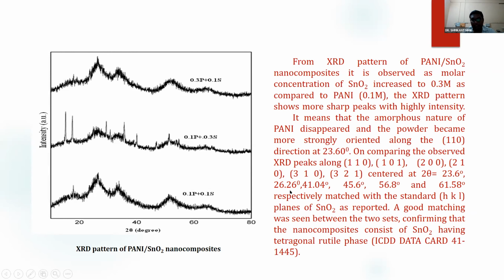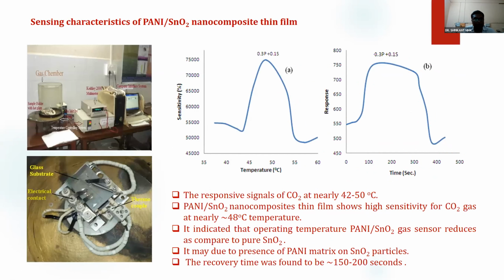And I compare this data with the JCPDS card number 41, which confirms the reported SnO2 peaks. That means in the polymer matrix, these SnO2 nanoparticles are incorporated very properly. So from these three characterizations, we can say that these polyaniline SnO2 nanocomposites have been properly formed. Now let's move on to the sensing characteristics of the PANI SnO2 nanocomposite.